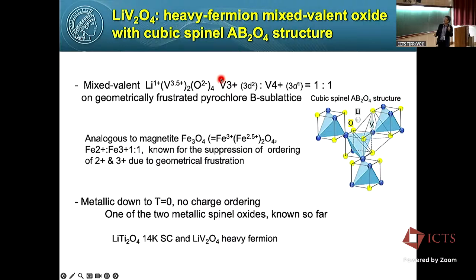In other words, we have a 1-to-1 mixture of vanadium 3 plus and 4 plus, 3d2 and 3d1, on a geometrically frustrated lattice. The situation is very similar to that of magnetite, where the B site iron has 2.5, a 1-to-1 ratio of 2 plus and 3 plus. And this compound is metallic down to T equals 0, no charge ordering. There are only 2 spinel oxides known to be metallic down to T equals 0. One is lithium vanadate, and the other is lithium titanate, which is a 14 K superconductor.